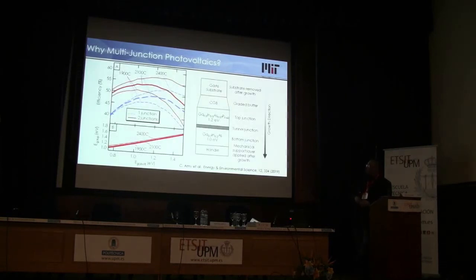Here's the reason we're interested in multiple junctions. So initial modeling predictions suggest that the difference between, let's say, here's one junction. This is just taking one curve for one temperature, let's say 1900 degrees C. You can see there's overall about a 5% boost you can get from adding a second junction. And so this is pretty attractive. And our colleagues at NREL have come up with some interesting designs for cells that try to actually eliminate buffer layers so that we can minimize parasitic absorption below the band gap.